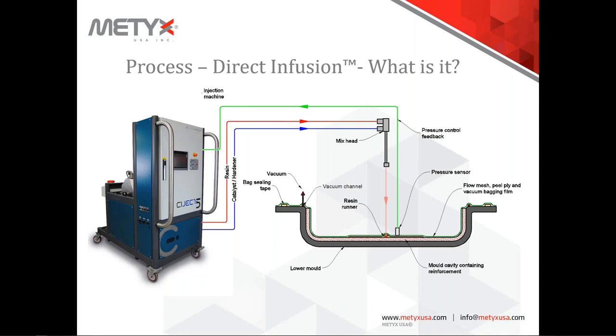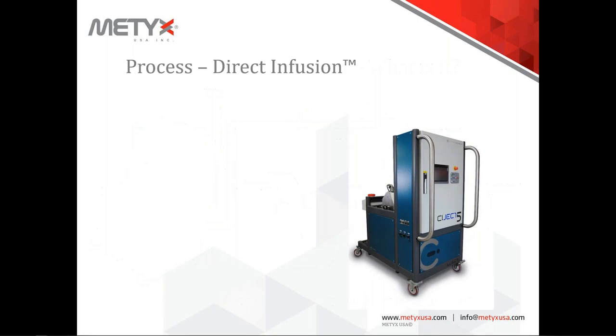But this has a pressure sensor feedback, and that's key to everything, to make sure that you have just the right amount of pressure, the resin is going in at the right pressure, where you're not ballooning that B surface tool, or if this is a nylon bag, you're not ballooning it out and having to wait for that resin to distribute again down through the laminate because you're forcing resin in too quickly. And that's really key to the whole operation.